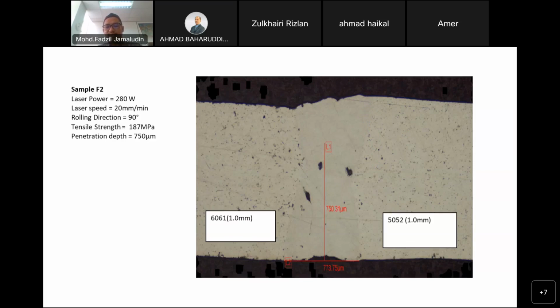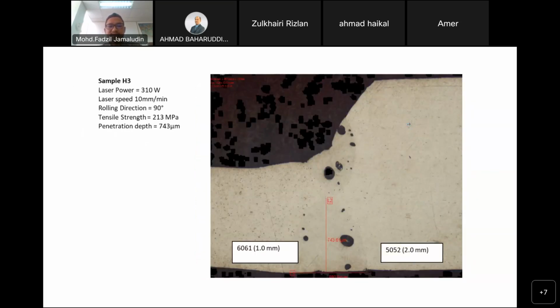of different materials, you can see that the weld is made without much difficulty, with no misalignment and so on. And this is another one on the dissimilar thicknesses. And even here you can see that there are no gaps. There are no lines of connection, showing that the weld is overlapping.